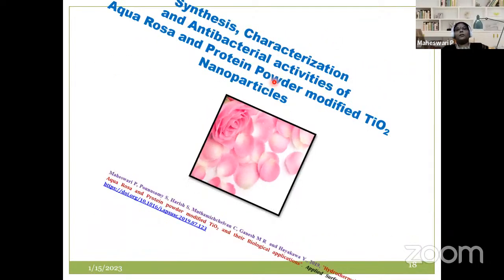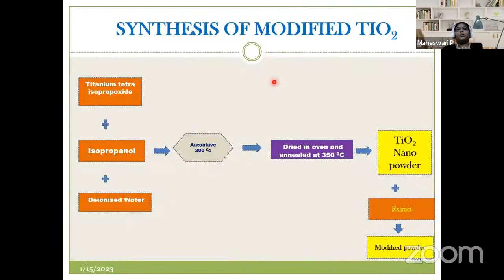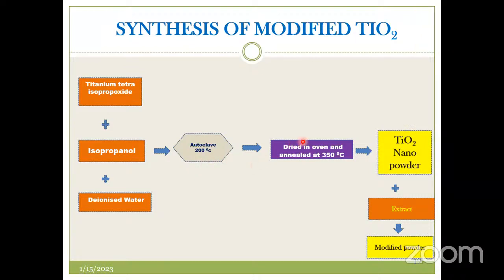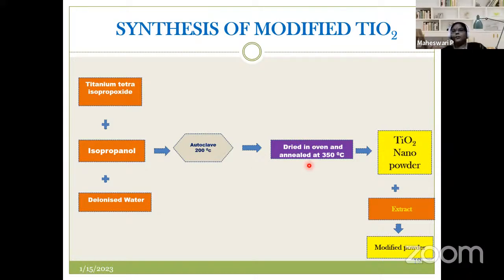So again, we went for the synthesis technique where titanium tetraisopropoxide, along with isopropanol and deionized water, were mixed together for nearly 2 hours. Then we transferred it to the autoclave at 200 degrees centigrade. After centrifuging and drying in the oven, we annealed it at around 350 degrees centigrade. So we got the nano powder.